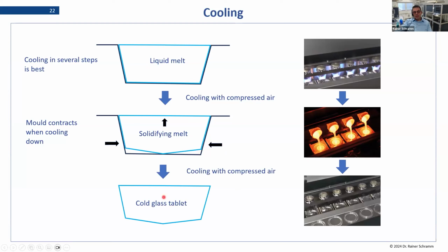You see that also the beads in the end, you can test them on a flat surface, and you will see that this is a bit not flat, but of course this is completely over designed, over exaggerated, just to give you the effect, to explain you why, if you use compressed air, the releasing is much easier than if not.